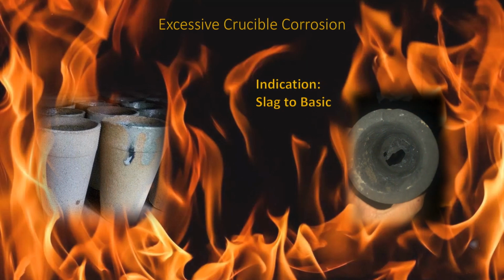Corrosion is not forgiving, and your crucibles will become corroded and unusable in time. If you find that your crucibles are being corroded faster than they should be, or if you find this nice hole in your crucible and a mess on the bottom of your furnace, you would not be the first to experience the losses. This dilemma is due to the fact that your charges may be too basic. Now, if this is the case, then try increasing the amount of your acidic flux.